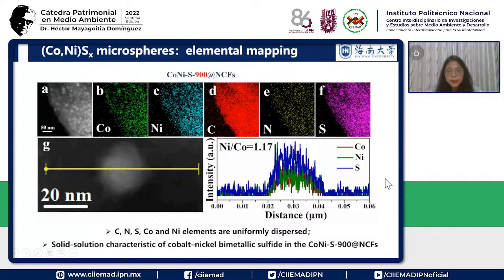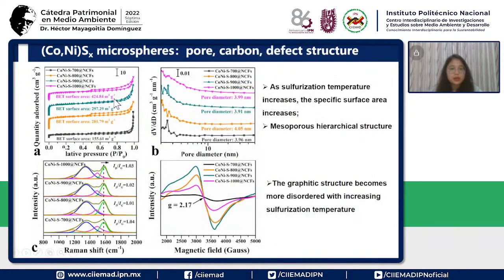This slide shows sample 900 here. We can also see all these elements are very uniformly dispersed, and here is a solid solution characteristic of the cobalt nickel bimetallic sulfide in the sample. And then we examine the pore, the carbon, and the defect structure here, and we can see that as the sulfurization temperature increases, the specific surface area also increases.